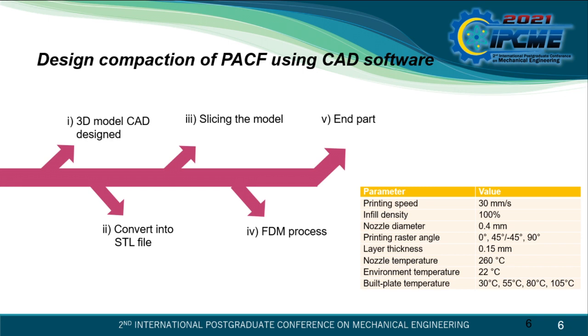The process started with the 3D CAD model design, which was converted into an STL file, then the model was sliced, followed by the FDM process, and then the end part. The design of PACF compaction using CAD software used some parameters and values, which I have included in this slide: printing speed 30 mm per second, infill density 100%, nozzle diameter 0.4 mm, raster angles of 0 degree, 45 degree, -45 degree and 90 degree, layer thickness 0.15 mm, nozzle temperature 260 degrees Celsius, environment temperature 22 degrees Celsius, and build plate temperatures of 30, 55, 80 and 105 degrees Celsius.